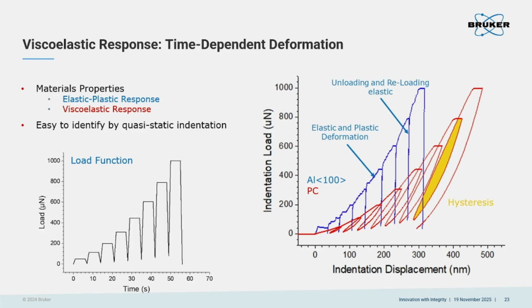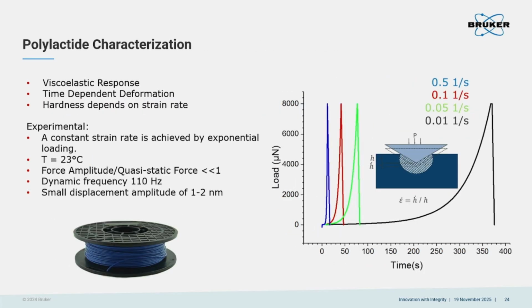This non-overlapping behavior is typically called hysteresis. That means the response will be different when decreasing the force than when increasing the force again. And a good way to understand this kind of behavior is the constant strain rate testing function, where you can see that the force is increased using an exponential function. I mean, the force increases with a different loading rate.